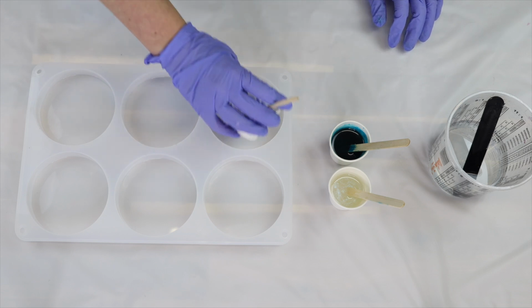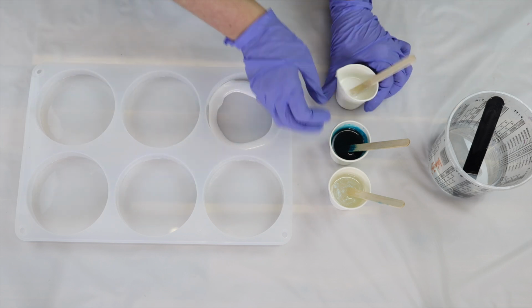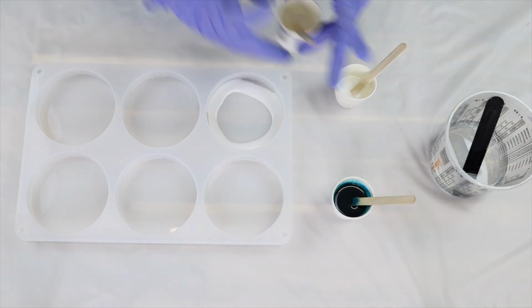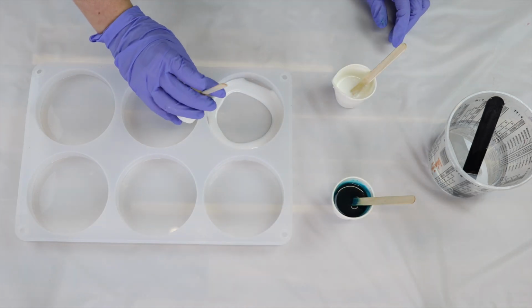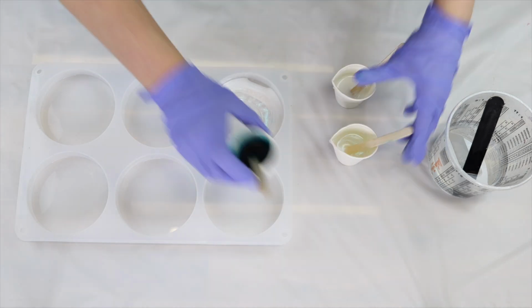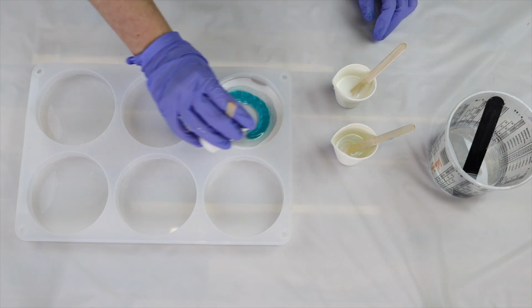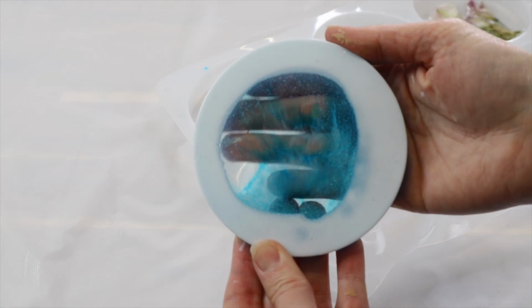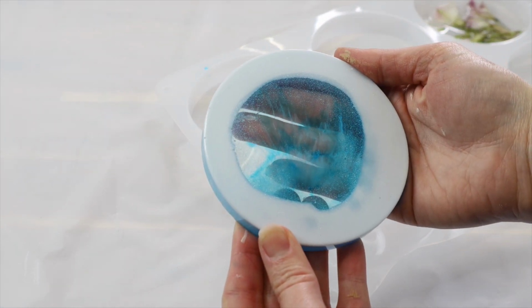You'll find that most of your cream pigments will generally be a lot denser than a powder or a tint. So if I pour my white down first into my coaster and then pour my tint and my powder down, because those are both lighter than my white, they don't have the ability to push that white up off the bottom, and therefore the white is just going to stay on the bottom of my mold.